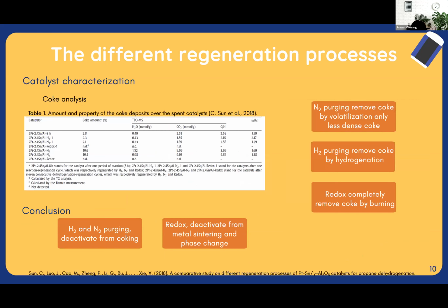For this section, the amount and property of coke over the spent catalyst are shown in table 1. The results show about 10% coke deposit on the hydrogen and nitrogen regenerated catalysts, blocking the pores of the alumina support, while no coke was detected with the redox method. Additional results show nitrogen purging removes coke by volatilization, only the less dense coke, but hydrogen purging can remove residual coke by hydrogenation. The conclusion of this paper: using hydrogen or nitrogen regeneration results in little impact on the size and structure of the metal active center. Redox regeneration can completely remove coke, but inhibits stability due to metal accumulation, phase transition, and a core-shell structure with an Sn-rich surface.